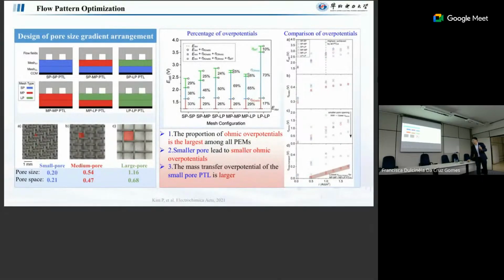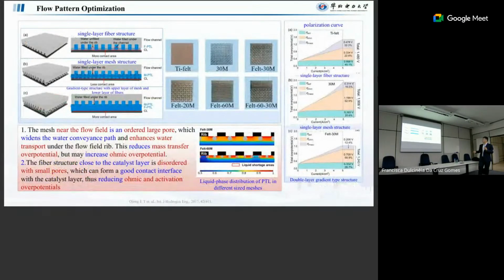But if we have a gradient system, that means we have a lot of contact between the nets. If we have a lot of contact, we have a problem called parasitic resistance. Then we create a lot of other problems. We have good mass transport, but not as good electron conductance. Another researcher did this work very well. For example, here they have only fibers, here only net. In the end, he put the fiber and net together and got good results. The reason is that when they put the fibers close to the catalyst, they have very good contact. And when they put the net close to the channels, they have very good transport of water and oxygen. For example, this one is too small, it's blocked inside. This is bigger, then it's okay. So they used this gradient and got very good results.